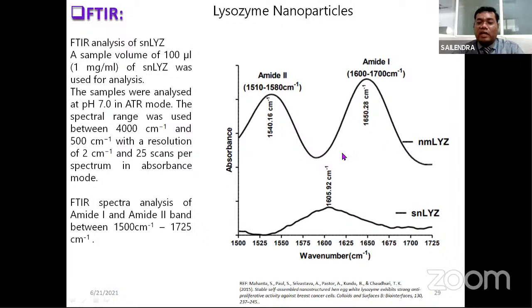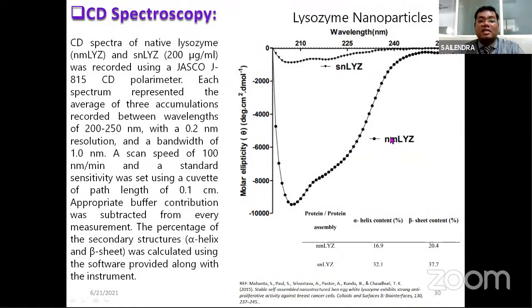So you see in native lysozyme, you will find the prominent peaks of these two amide bands. Whereas in case of nanoparticles, due to cross-linking of these amide bonds in the protein, you won't find these two bands, and rather you will find one small band, which is around 1605 centimeter inverse for lysozyme. So this is for representative purposes only. You can also characterize with the help of FTIR analysis, and you can observe these amide 1 and amide 2 bands. Next, you have to go for CD spectroscopy.